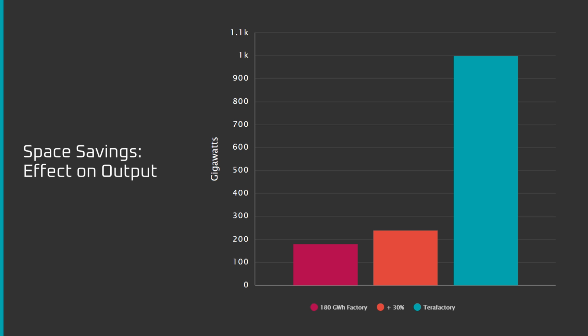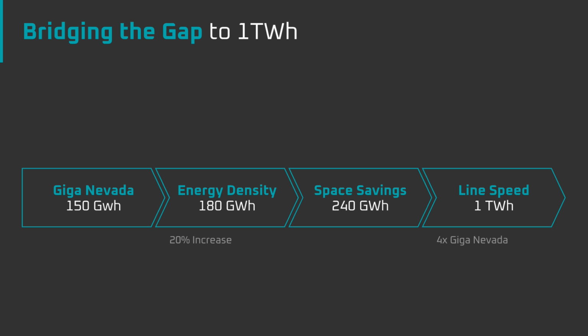The only other way to make up the gap between 240 gigawatt hours and 1 terawatt hour is to speed up the lines. In other words, if Tesla intends to build a Terafactory with Maxwell DBE lines using the same size footprint as Giga Nevada, our calculation would be 1 terawatt divided by 240 gigawatts. This means that the Maxwell lines would need to achieve at least 4.16 times the output of the Panasonic manufacturing lines at Giga Nevada. We'll call it an even 4x.